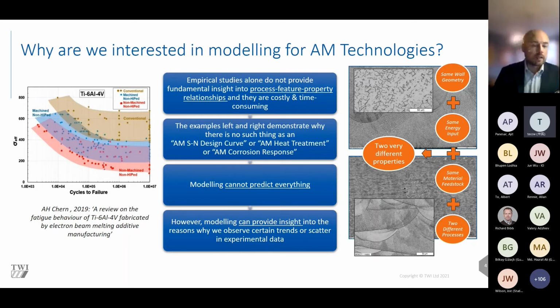If we look on the left, you've got some SN curves for the fatigue performance of a TI-64 part. And you want something to last, say, 1 million cycles, you can find any stress range on that plot where it failed. Now, yes, that's a little bit of an abuse because some of that's machined and hipped and not hipped, but it's very indicative and representative of what we see with a lot of fatigue behavior of additively manufactured parts. It's not just down to a material, but it's the material, the process parameters, the surface treatment, and any number of factors that ultimately influence the performance of that part.